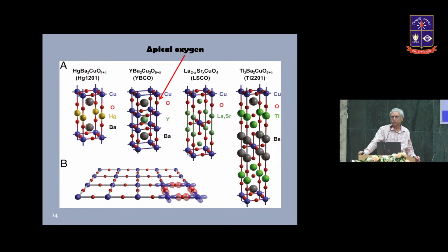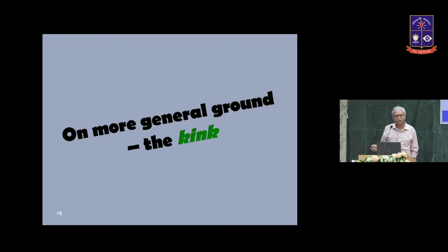In copper oxide superconductors, people did these phonon experiments, and we have done it extensively. For isotopic substitution, we have used O16 and O18. So basically, when we make copper oxide superconductors, it's mainly oxygen 16. In a carefully conducted experiment, we can exchange almost 95% or 98% of this O16 with O18. And we track what happens to the superconductivity as we substitute the oxygen with the heavier isotope. And the result we receive is very strange. I'll get to that.